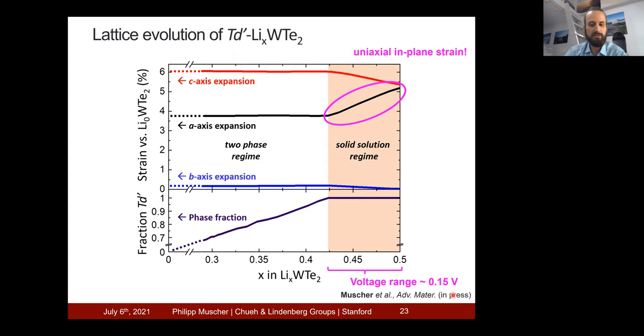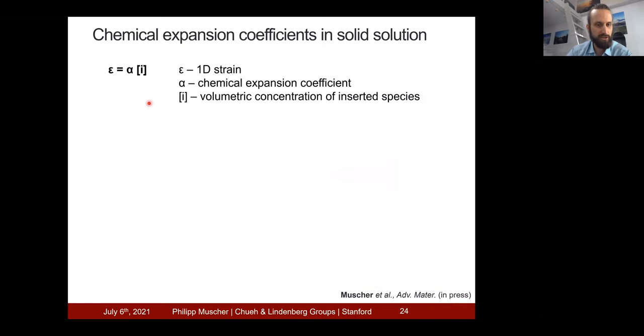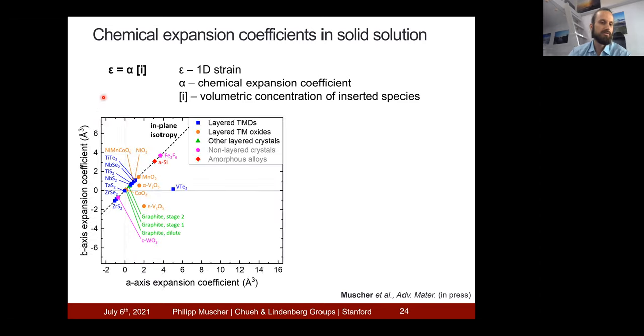So this made me curious what the chemical expansion coefficient in the solid solution actually is, because it seems to be very large. The chemical expansion coefficient is the alpha in this equation over here, which is essentially the proportionality constant between the volumetric concentration of inserted lithium and the resultant strain. So here are the in-plane chemical expansion coefficients for a range of prominent lithium insertion materials.